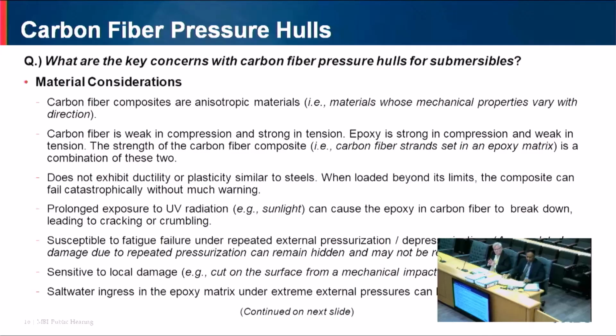So the next thing is carbon fiber composites do not exhibit plasticity or ductility similar to steels. If you look at the stress strain curve of carbon fiber composites, the relationship between stress and strain is nearly linear up to the point of failure. Okay. So this curve does not have a well-established yield point because there is no yielding of the material. So the material goes all the way to its failure point and then it catastrophically fails with little or no warning. So this is very different from traditional materials such as steel or titanium.